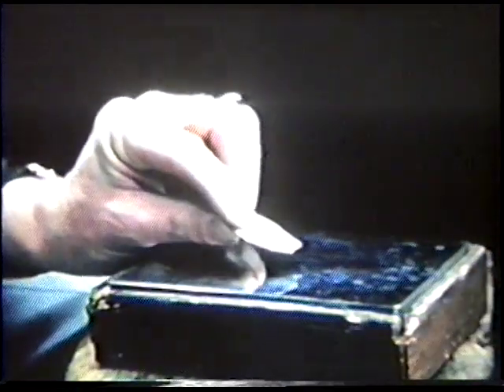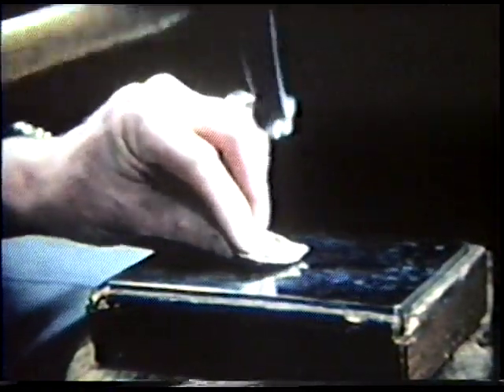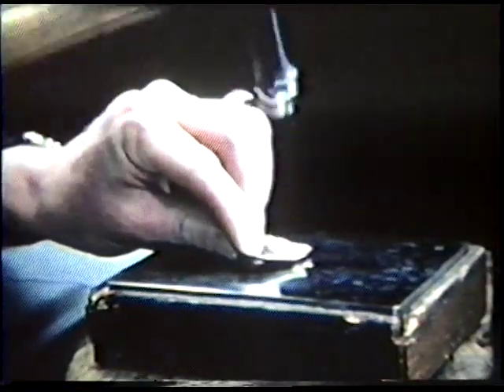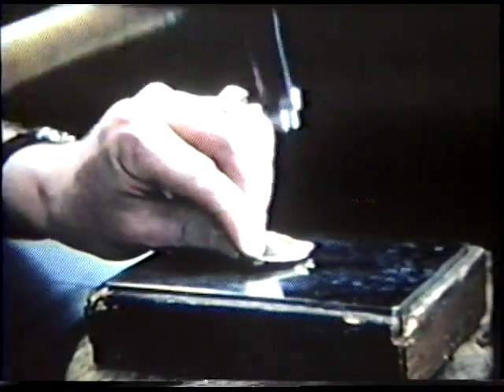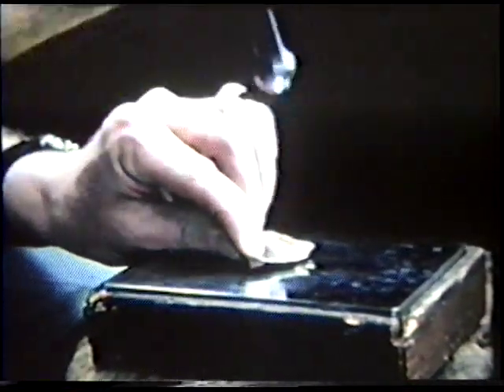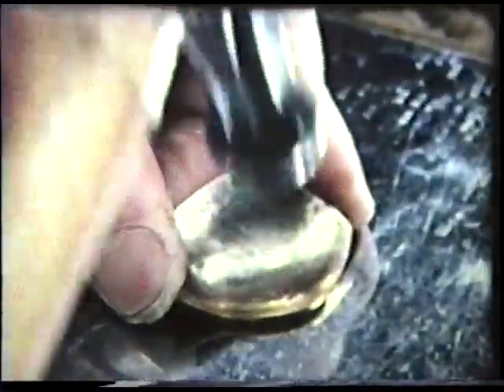The hammering is continued with the same hammer against a steel plate. The hammer blows are kept away from the edge so that it retains its original thickness as the central area becomes thinner and the depth of the depression is increased.